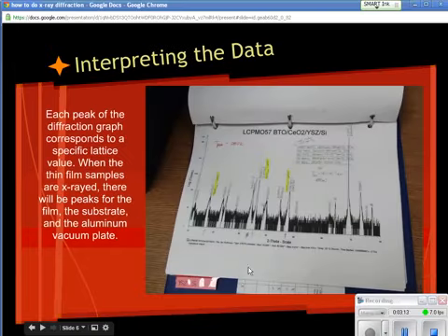And it measures the peaks according to Bragg's law that you saw when you investigated X-ray diffraction, and each of these peaks corresponds to a particular location in the lattice, and this is an example of LCPMO, which is lanthanum, calcium, praseodymium, manganese, and oxygen in the sample, and these are the 4 targets that the sample was deposited with, and the last thing is the substrate that it was deposited on, which is silicon.